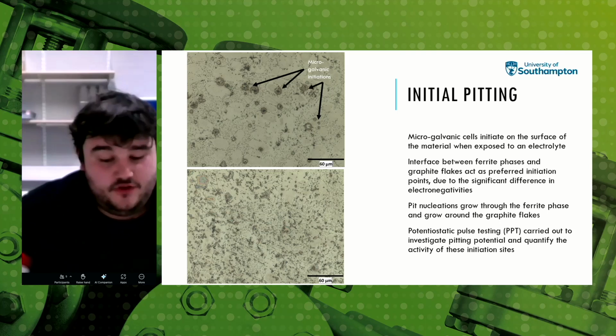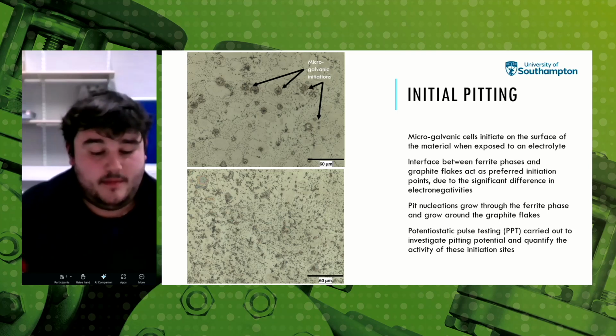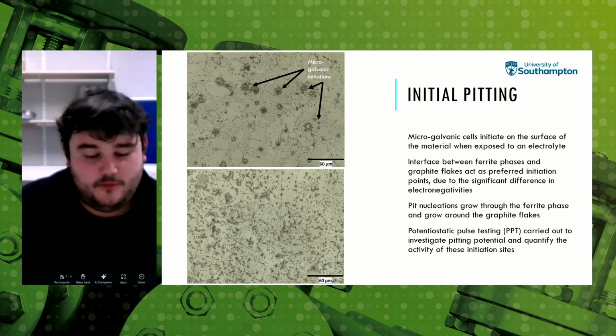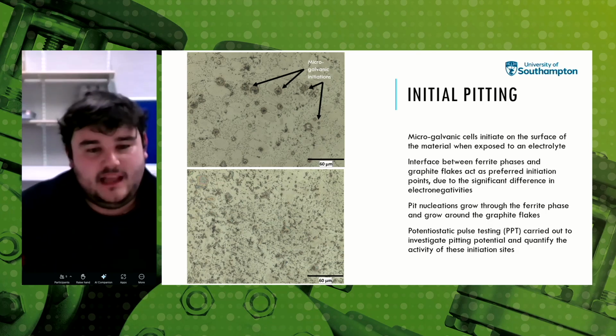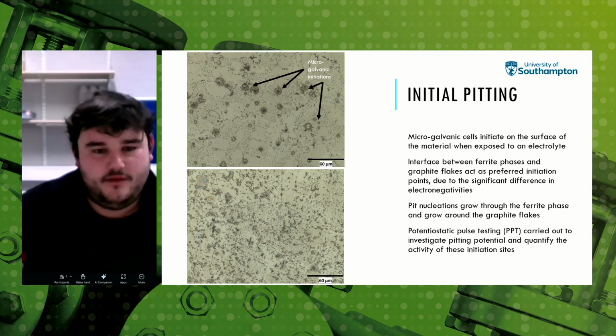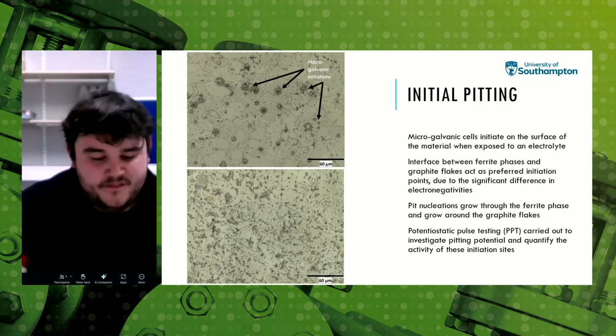So these ferrite graphite regions are incredibly susceptible to corrosion damage, as these two separate phases have a large difference in electrical activity, which allows these microgalvanic cells to form on the surface when they're exposed to an electrolyte. So on the left, we have some small spots. On the top left, those are pit initiations. They are the very start of a corrosion process on the surface. And as they propagate, that becomes more severe and develops into a uniform corrosion process. So they're effectively the very start of the corrosion career.